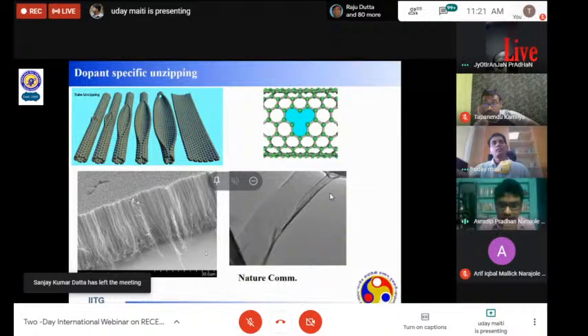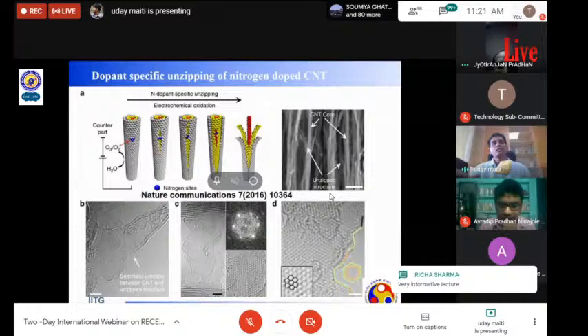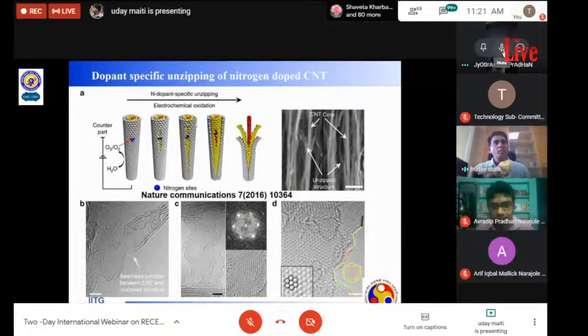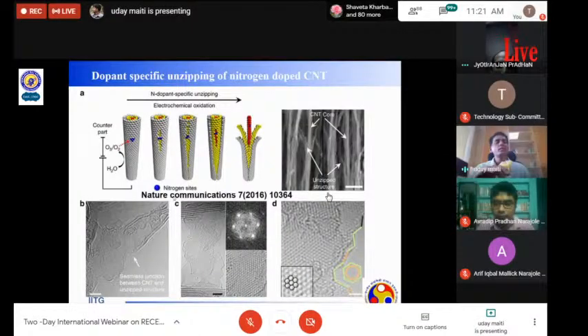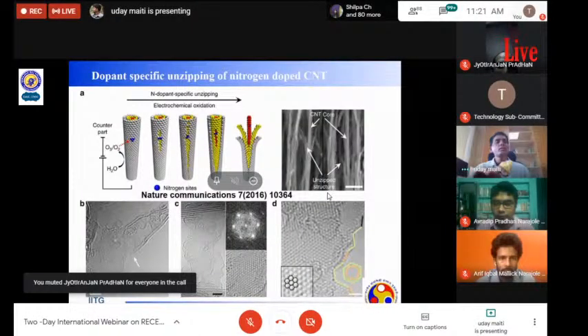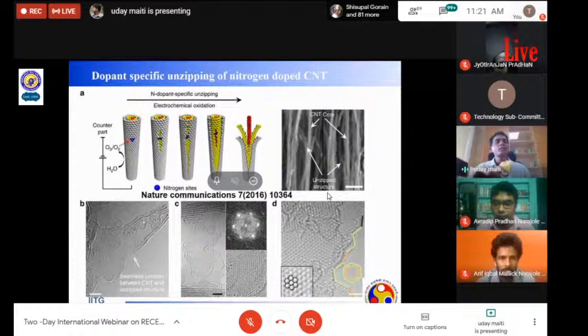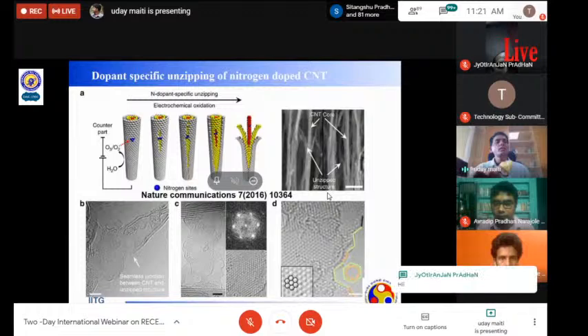Okay. So here we did some dopant-specific unzipping. This is a carbon nanotube. When it is unzipped, it gives rise to nanoribbons of graphene, and this is the specific process by which we have done it so that it remains crystalline in nature. So it is very different from the other reported methods, where there is a lot of disorder.